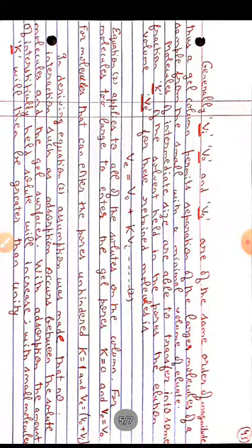Equation 2 applies to all of the solutes on the column. For molecules too large to enter the gel pores, K will be equal to 0 and VE is equal to V0. For molecules that can enter the pores unhindered, K is equal to 1 and VE is equal to V0 plus Vi. In deriving equation 2, the assumption was made that no interaction such as adsorption occurs between the solute molecules and the gel surfaces. With adsorption, the amount of interstitially held solute will increase.